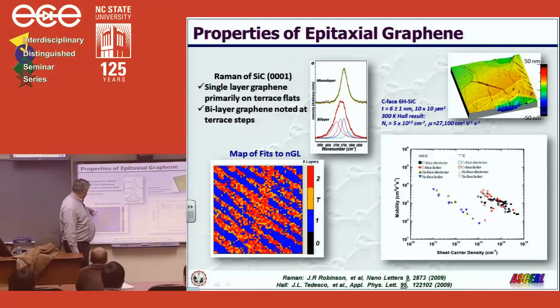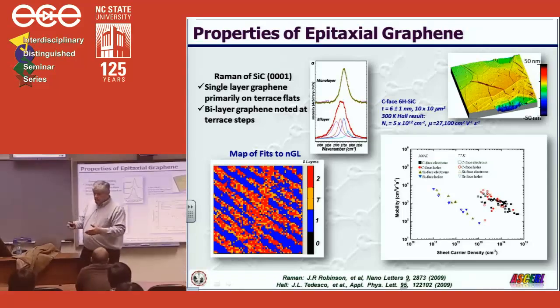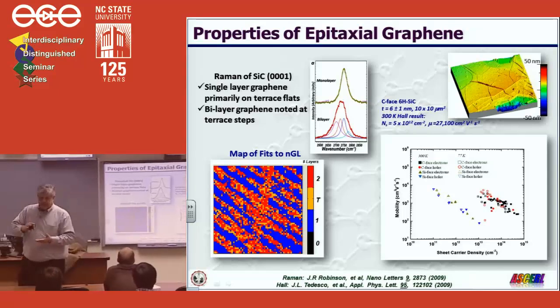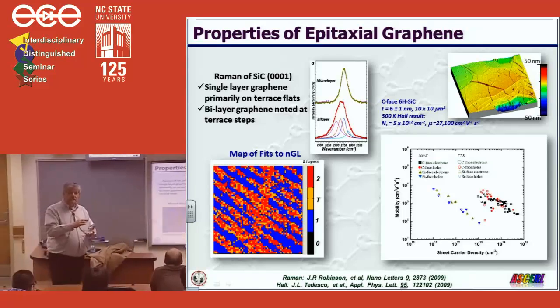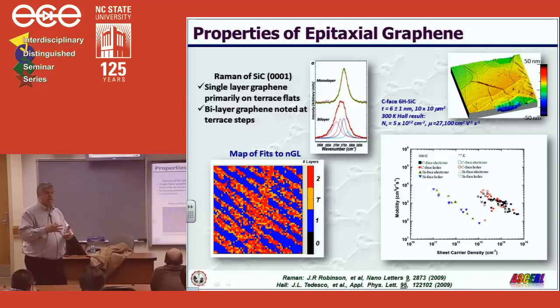You notice that you get these areas that consist mainly of 1 layer separated by areas that are about 1 to 2 layers. This is actually the step and terrace pattern that I showed you in the AFM. You could overlay them, and you will see it overlays precisely. As you saw in that TEM image earlier, when graphene goes over a step, it tends to have more than 1 layer. So something is happening in the growth process that adds a layer. Not well understood.